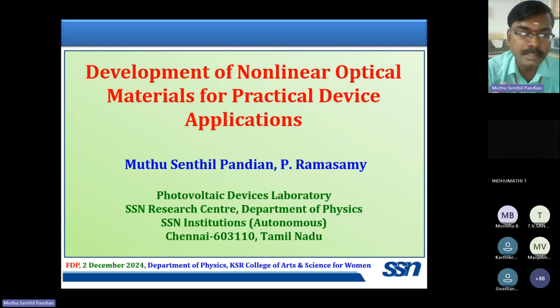So as a seed crystal, we can use the same efficient single crystal, mounted at the bottom of a large size glass sample, and we grow the same highly efficient material by another method called the Sankaranarayanan Ramasamy method.